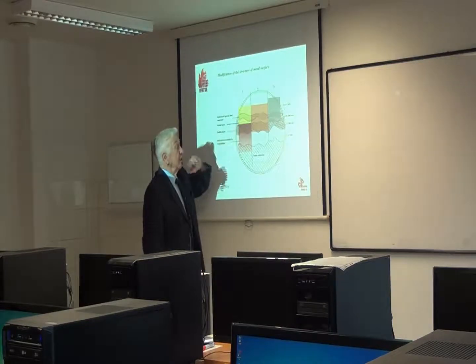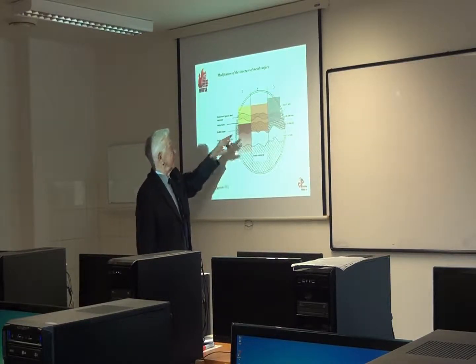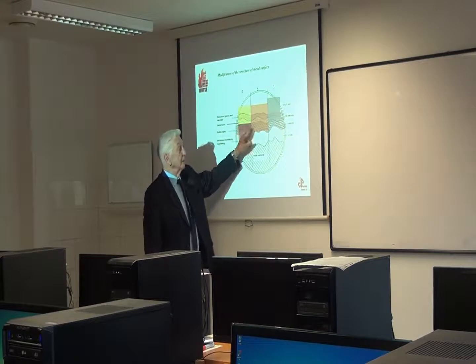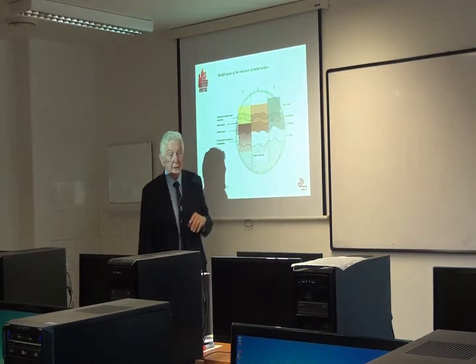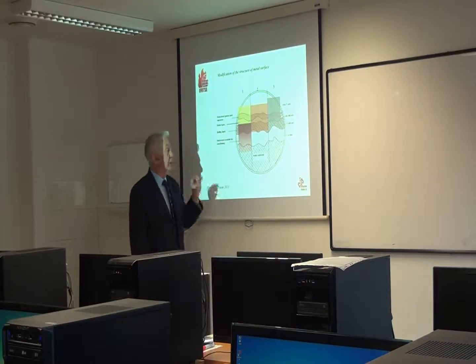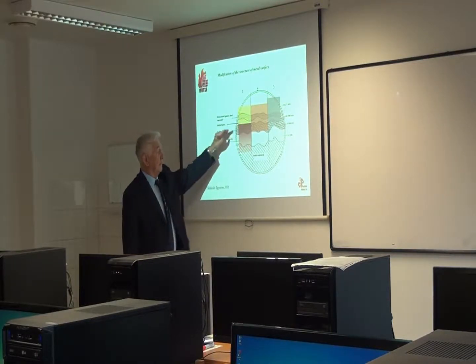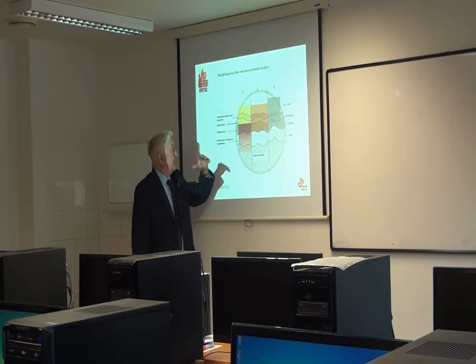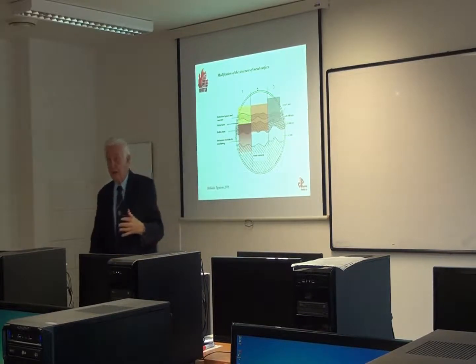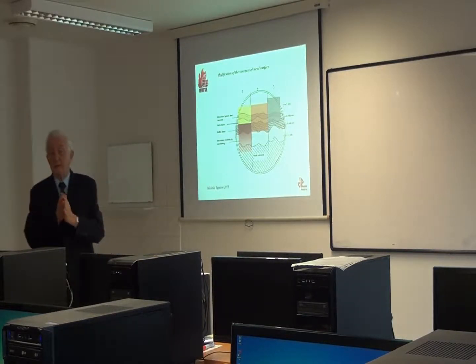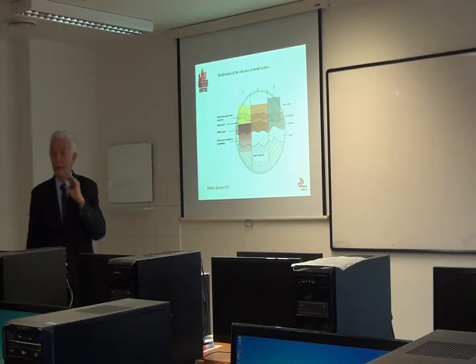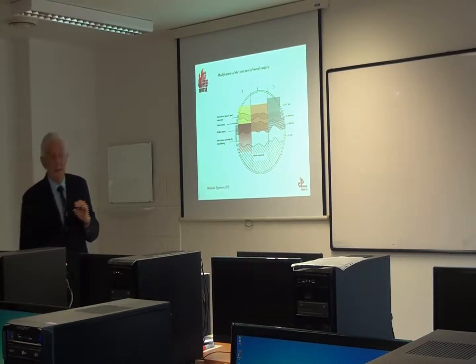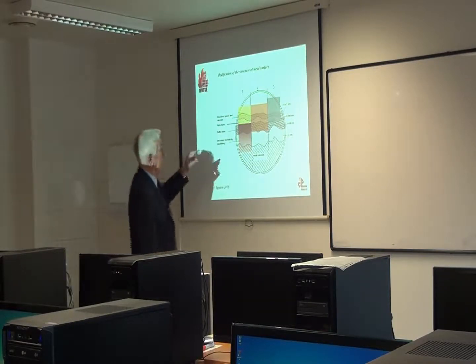Then comes a very interesting layer, the so-called Beilby layer, of 1 to 100 nanometer dimension, which is practically an amorphous layer. The crystals are destroyed in such a manner that we cannot anymore talk about the crystal structure. It has very special properties, a kind of amorphous layer.